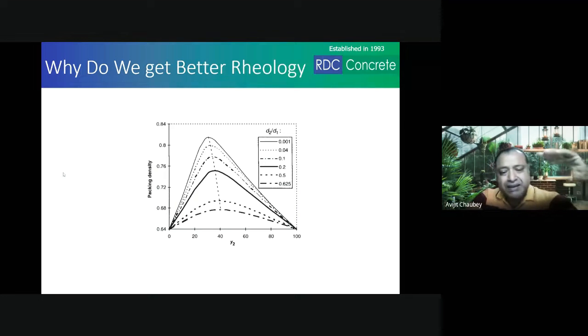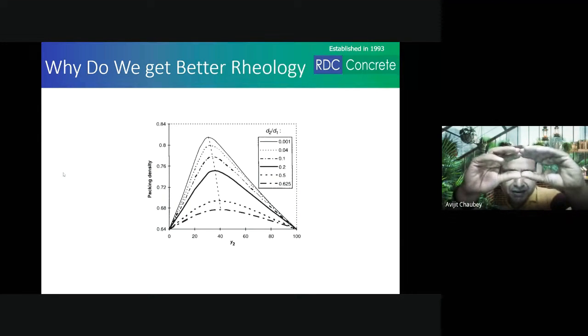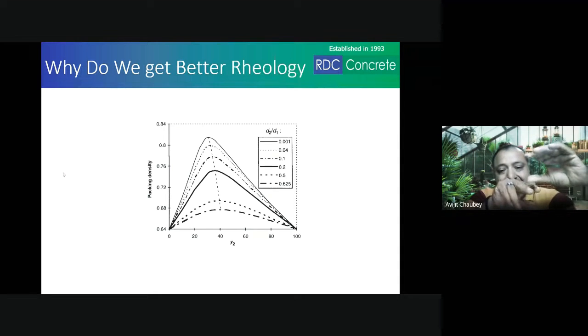In uniform particle packing, if you have got 20 aggregate, the assumption was that the voids are 10 in diameter, half the size. So all the sieves that you use for sieve analysis of the aggregates are half in size: 20, then 10. Below 10, the sieve is 4.75, which is very close to 5. Below 4.75 is 2.36, and so on. All these are half. And the proportions of these materials are such that each material has to be there. And many people get annoyed when they see some middle part of the material is missing.